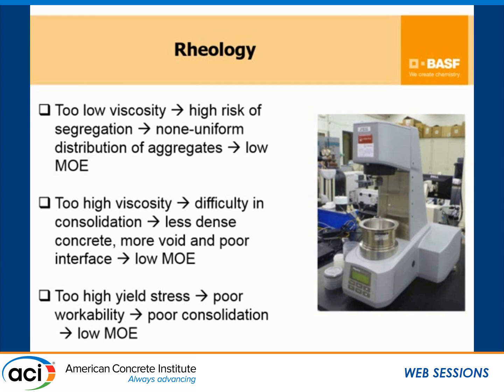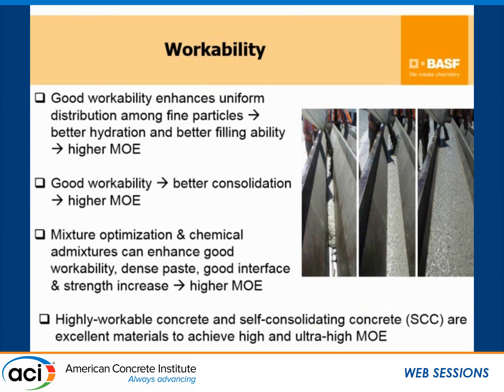Regarding rheology, too low viscosity creates a high risk of segregation, leading to non-uniform distribution of aggregate and low MOE. Too high viscosity makes consolidation difficult, creating more voids and poor interface, which can also lead to low MOE. Too high yield stress can lead to poor workability and poor consolidation. Workability enhances uniform distribution among fine particles, better hydration, better filling ability among particles, and therefore higher MOE. Mixture optimization, chemical admixtures, and temperature can enhance good workability, dense paste, good interface, and strength increase, therefore enabling higher MOE.